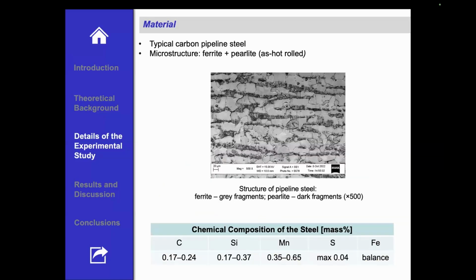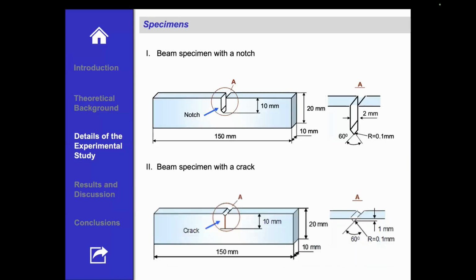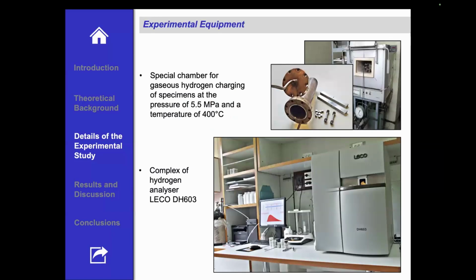We studied typical carbon pipeline steel, and we produced two types of specimens: a beam specimen with a notch, as maybe some type of corrosion defect, and in the next case a beam specimen with a crack. In the experiments, we used a special chamber for gaseous hydrogen charging, and to examine hydrogen content, we used the LECO analyzer, which shows the hydrogen content in the material.